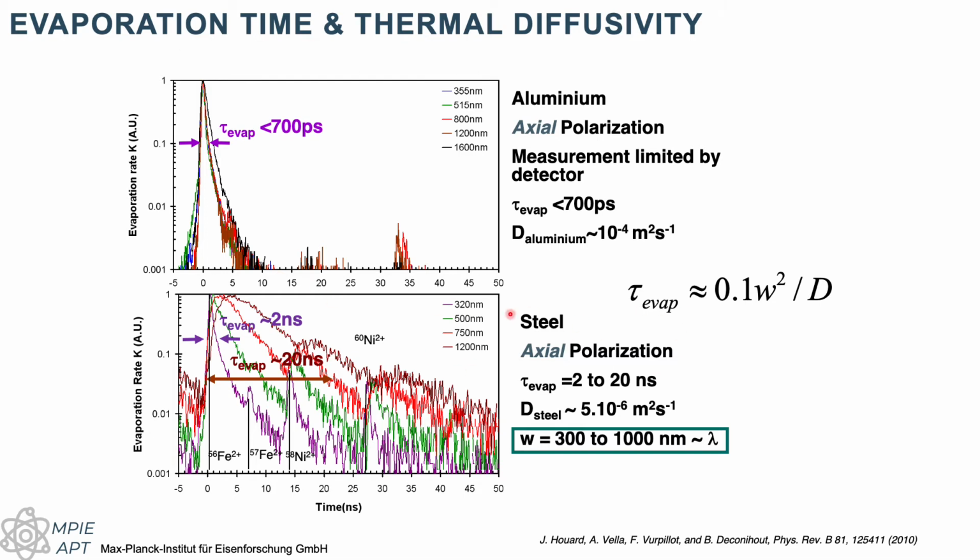But if you take a piece of stainless steel that is not as good a heat conductor, it will take a long time for the heat to travel along the shank and back. So you're going to have a very strong dependence on the wavelength. If you look at these peaks, not all of them would be acceptable. And all of this would be dependent on the heat diffusivity.